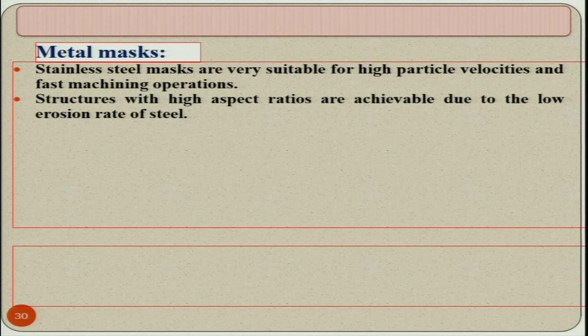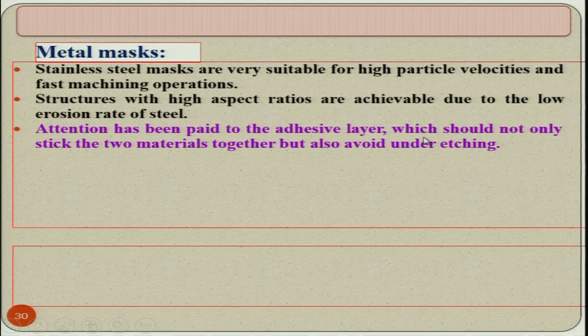Metal masks made of stainless steel are very suitable for high particle velocities and fast machining operations. Whenever you have high particle velocities, their kinetic energy will be high and they can erode the mask itself. But since it is made up of stainless steel, the erosion rate will be very low and it will not affect the shape and size of the mask, which is going to govern the shape and size of the feature or the pattern created on the workpiece surface. Structures with high aspect ratio are achievable due to the low erosion rate of steel.